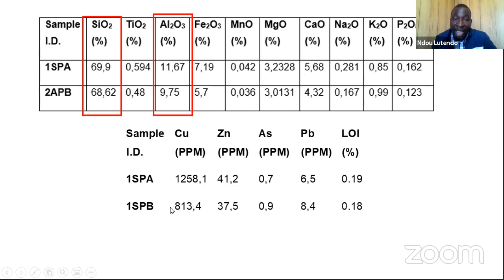And we had high concentration of copper, which is in ppm, and it was over 800 on both samples. You can see this one was 813, and this one was 1,258.1. Part of the reason why copper is higher is because these tailings were taken in a copper mine. So obviously there used to be a residue, but you can see a range of other metals such as zinc, arsenic, and lead. And these are toxic materials that should not be in the environment.